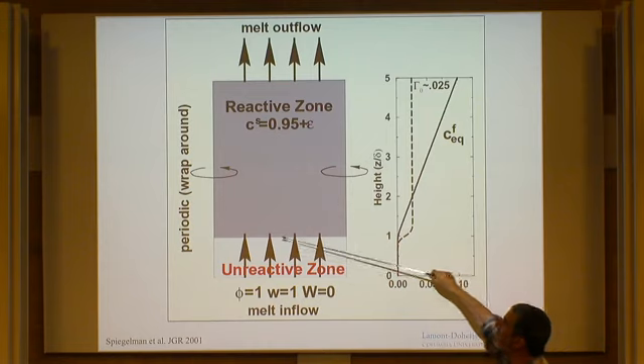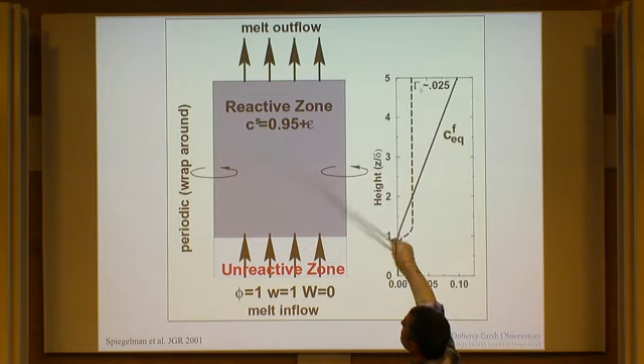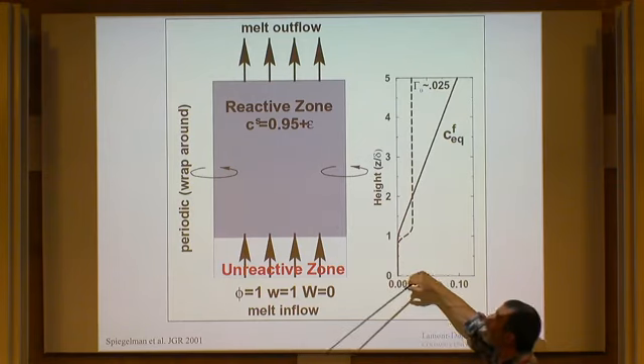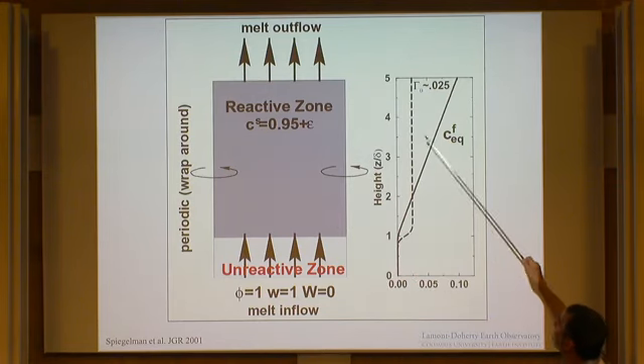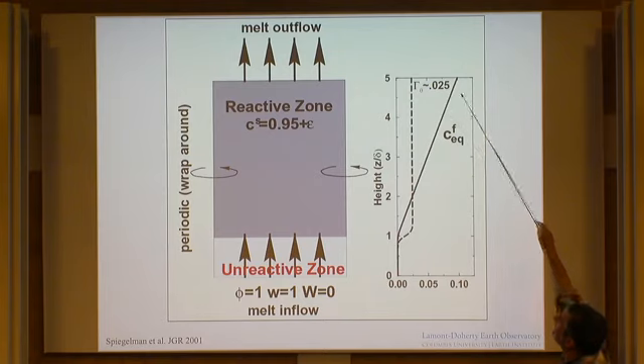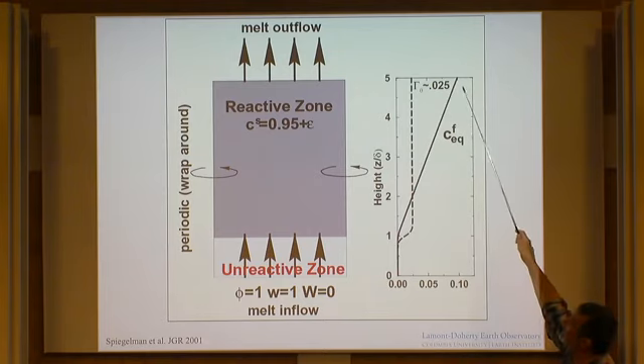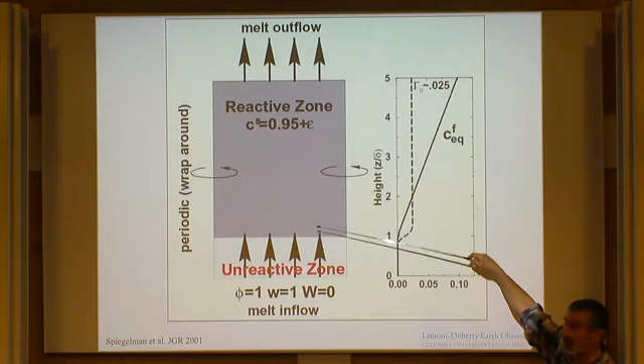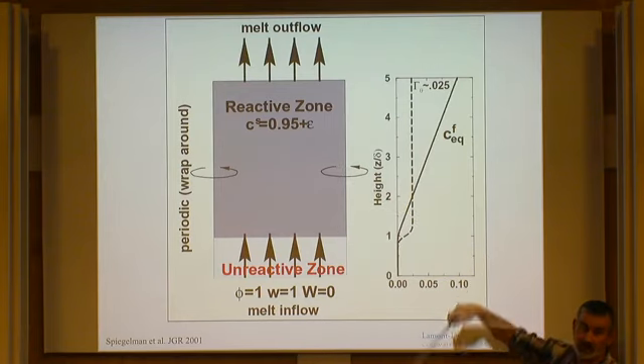So we have a viscous porous matrix, which is partially soluble. We have a solvent coming in the bottom. In this first set of models, the solid didn't go anywhere, so it just corrodes and corrodes over time. And we have a gradient in the solubility of some solid phase, just like the lattice-Boltzmann model that I showed you before, and it's a linear gradient.